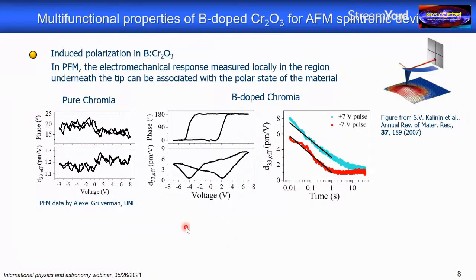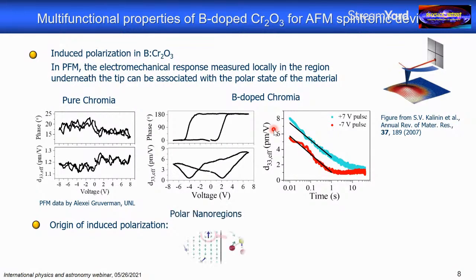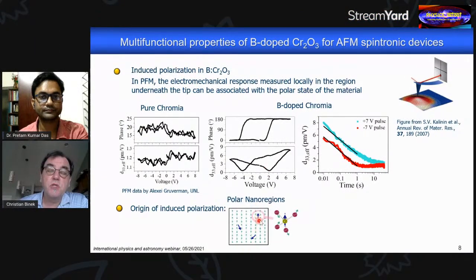So these were data taken by my UNL colleague, Alexei Gruverman. He's an expert in all things scanning probe microscopy. Now, we could speculate a little bit about what is the origin of this induced polarization. And the idea here is that we have polar nanoregions. That means regions where symmetry is locally broken and you have a relative shift of the ions relative to each other and creating local dipoles. And then if you apply an electric field, that dipole is oriented and creates polarization.